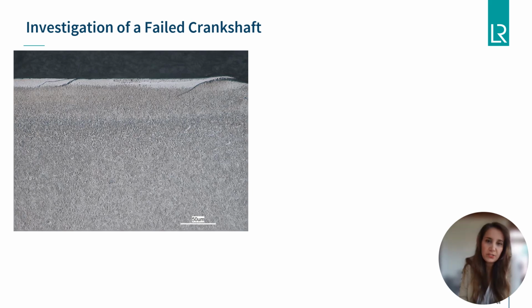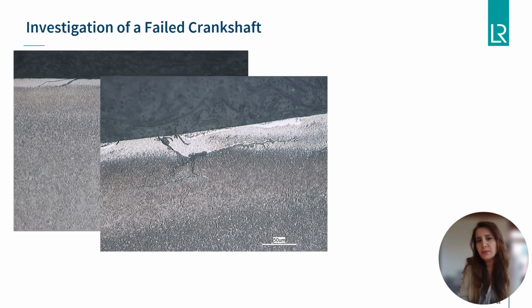Further examination of the external surface of the main bearing journal revealed evidence of cracking associated with the spalled areas, some of which had propagated parallel to the surface. In several areas, the spalling and cracking observed was associated with a white etching layer considered likely to be untempered martensite. White etching layer can be intentionally produced to create a surface hardened layer.